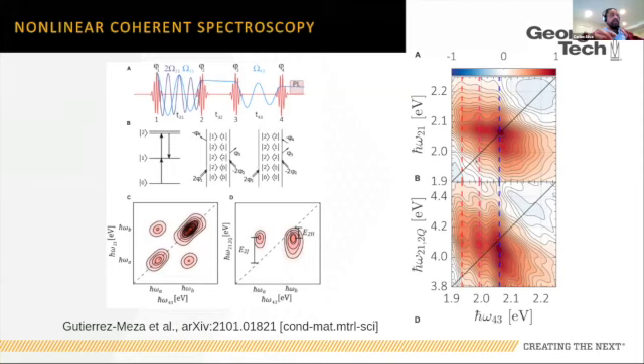Now, the key result, and this is where I will emphasize, is that when I now do my 2 quantum coherence experiment, so this is a 1 quantum coherence, here's a signature of the 0, 0 of the H aggregate, here is a weak signature that we interpret as a 0, 0 of a J aggregate, here's another peak that is perhaps another progression of the J aggregate, strong cross peaks with this.